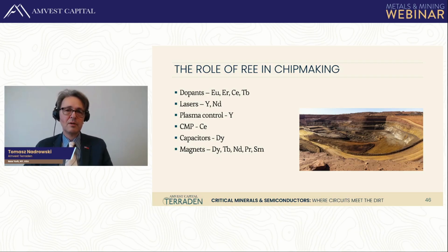For plasma control, we also need magnetic fields, so the magnets, such as the neodymium iron boron magnets, are really important. And if we're talking about magnets, it's also important to keep in mind that a lot of the machinery in a semiconductor foundry, such as in Taiwan, depends on those magnets for magnetic levitation. So a lot of machinery, there's no physical contact. So there's a lot of frictionless, contactless presence as these different parts moving in lithography or in metal deposition, whether physical vapor deposition or atomic layer deposition or chemical vapor deposition. This is where the magnets are absolutely necessary. Some of these magnets are apparently also the cobalt samarium magnets.